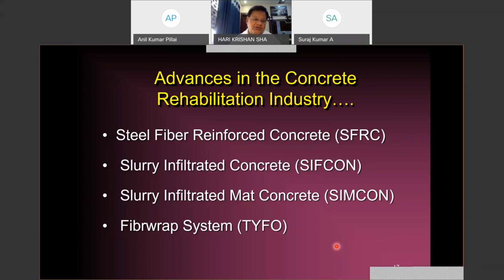So it is just like conventional reinforcement. We put the longitudinal reinforcement along the shorter span in the case of slabs, and some reinforcement is also provided along the longer span, which is regarded as the secondary reinforcement. The same concept was used to develop this material, wherein 60 to 75% of fibers were laid in one direction, and 30 to 40% of fibers were laid randomly in the other direction. And the rich cement slurry was injected over these steel fibers.